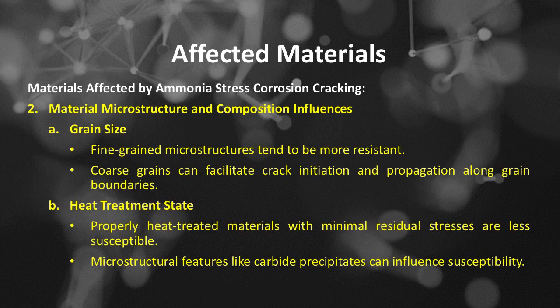Material microstructure and composition influences that may affect ammonia stress corrosion cracking include, number A, grain size. Fine-grained microstructures tend to be more resistant. Coarse grains can facilitate crack initiation and propagation along grain boundaries. Number B, heat treatment state. Properly heat-treated materials with minimal residual stresses are less susceptible. Microstructural features like carbide precipitates can influence susceptibility.